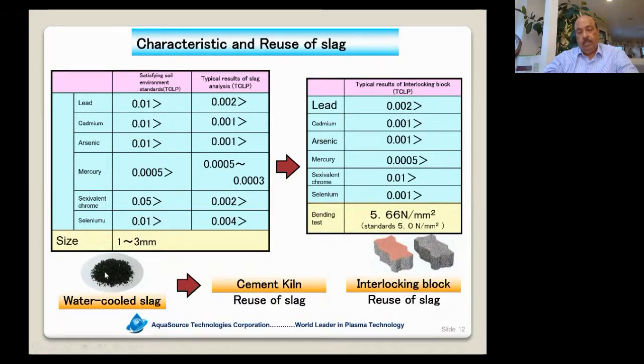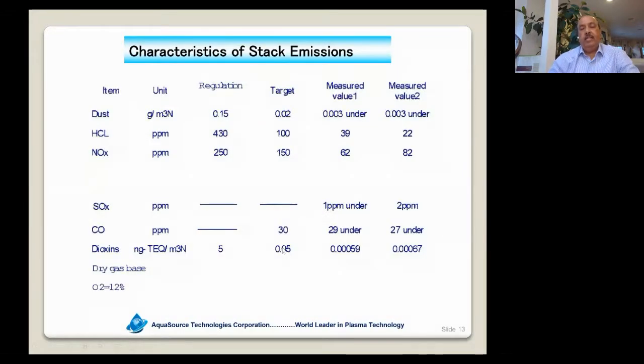The slag then comes out after the water-cooling slagger in 1 to 3 millimeter size, and for that particular plant, they make it into interlocking blocks. The TCLP on the interlocking blocks is shown here, which is orders of magnitude less than the requirement. For the cement kiln, we propose that the water-cooled slag can be fed to and reused in the cement kiln. I want to show you on the next slide the stack emissions.